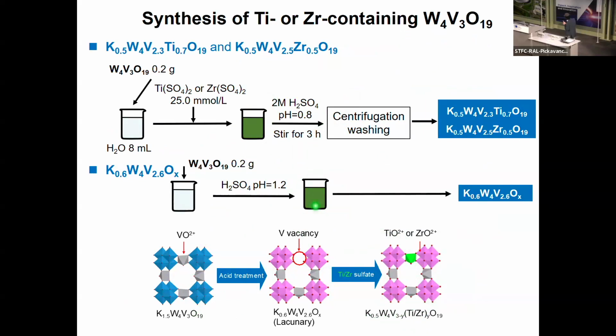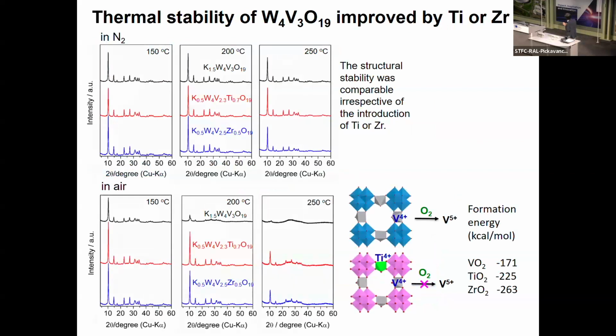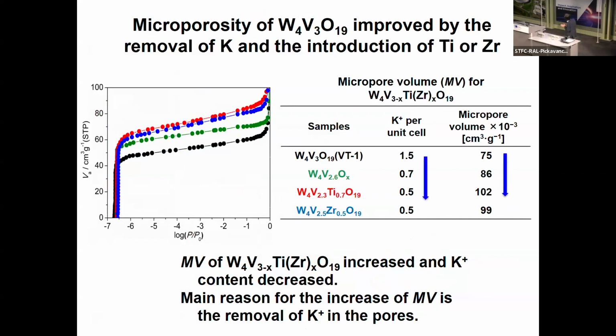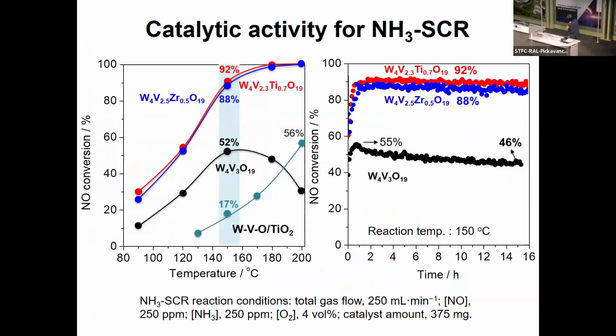The strange thing is that we can only remove one vanadium, and we can only introduce one titanium or zirconium. There must be something tricky going on in these systems, but nevertheless, it works, and we can get very stable structures, and even the microporosity is enhanced because we remove some amount of potassium existing inside. Therefore, we can expect higher catalytic performance. Yes, it works. As you can see in the data on the left-hand side, the titanium-containing or zirconium-containing catalyst shows much superior activities to this type of catalyst. Again, this is much better than the industrial systems. More important is that the stability is much higher than this. So in this case, I think we overcame the thermal stability problem by introducing the titanium.